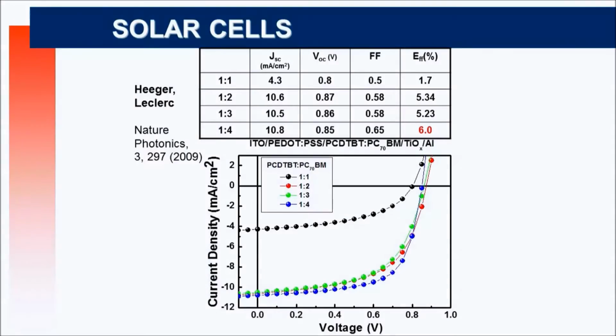So we got quite nice results with this one. And with Konarka and Alan Heeger at that time, we were the first to publish an efficiency above 6%. So for some reason, everybody was blocked at 5% with P3HT. It was the first example of a polymer designed for solar cell application that could give an efficiency of 6%. At that time, that was the world record. It survived 6 weeks probably, and someone got much better results. But it shows that it's possible to make what I call a rational design of polymer for solar cell application.